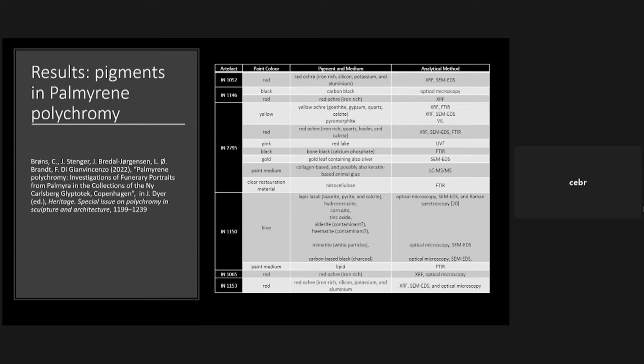VIL imaging has not revealed any convincing traces of Egyptian blue on the portraits examined. In some cases, a few brightly luminescing particles are observed. However, they seem to be unrelated to the polychromy. Firstly, the distribution of the luminescing particles appears quite random. Many of the particles are found on heavily abraded areas that have never been painted. And secondly, no blue particles have been identified in the corresponding locations.